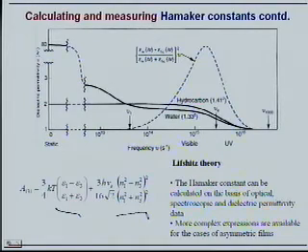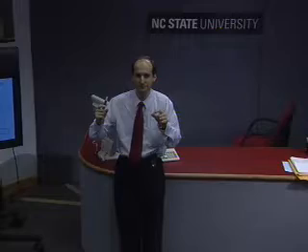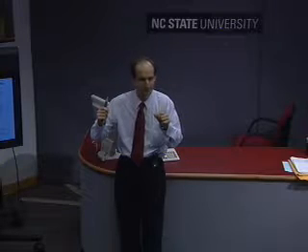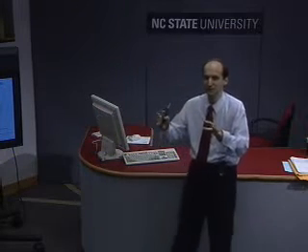If the phases have the same refractive indices, they're going to have the same Hamaker constants, unless they have high polarizability, which is not likely for most of the common substances. So two polymers, for example, are going to have exactly the same Hamaker constant exactly when they have the same refractive index. And this is one very simple rule of thumb way to compare Hamaker constants and obtain them.